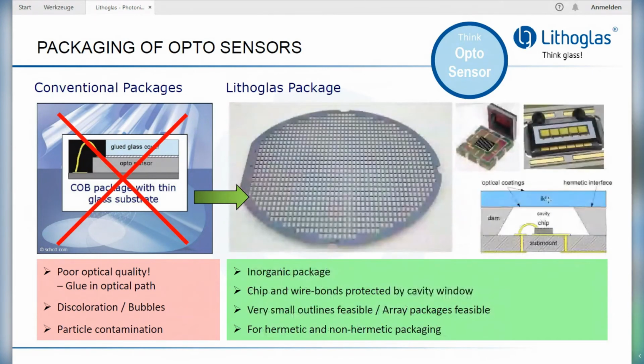Again, also with sensors, we can use our lid concept, and you have an assembly on a flat submount and provide a lid. In this case, it's a glass-silicon compound to cover it, for packages like sensors, but also LED. And the hermeticity that's achieved just depends, of course, on how it's attached and what kind of submount you choose. So you can see here the FR4 is clearly not hermetic, but it's hermetic enough to be qualified for an automotive product.